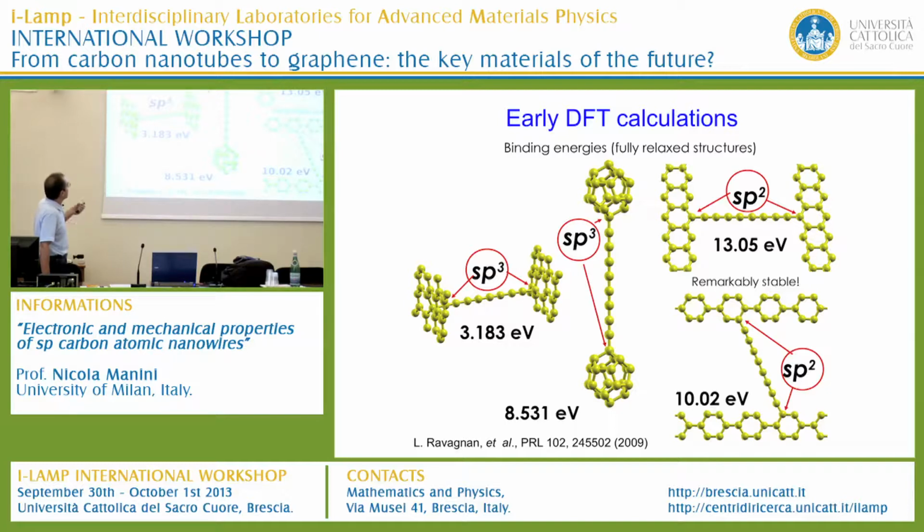For example, small fullerenes, like here, where there is a binding to an sp3 site; to graphene, on the sides of the graphene surface, on top of the graphene surface, where binding would not be particularly favored; and also to graphenic edges, like here, where indeed the binding energy would be much stronger.